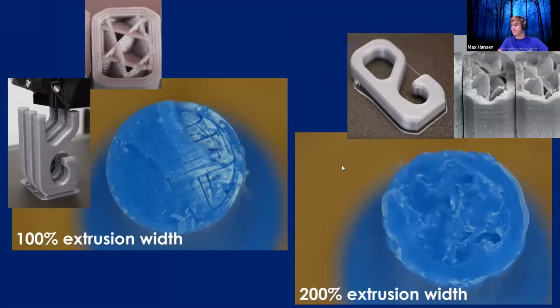So then on the left, you can see here at this 100% extrusion width, you end up having a lot of these little holes and cracks and crevices like this, where the print didn't quite connect with itself and didn't bond very well. And then, like I said, you end up with a clean cut, which is something you usually want to not have, right? You want to avoid this as much as possible. And this looks a lot like our break from earlier with this 3D printed hook. So you want to be thinking of ways that you could fix this.